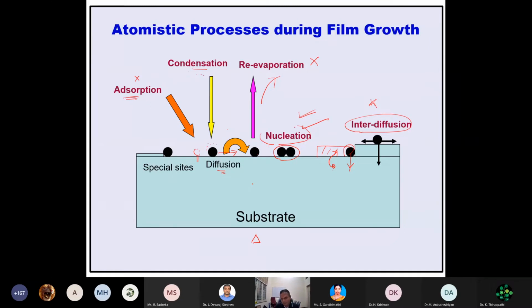Okay, so when you are going to adopt a particular technique like PVD or CVD, you have to understand the principle behind that particular technique. And then you have to see which atomic processes will happen dominantly, and you have to adjust your substrate temperature, distance, and the evaporation rate, all those things, such that nucleation is dominant, and re-evaporation and the like are minimized. Okay, you have to fix the substrate temperature accordingly.